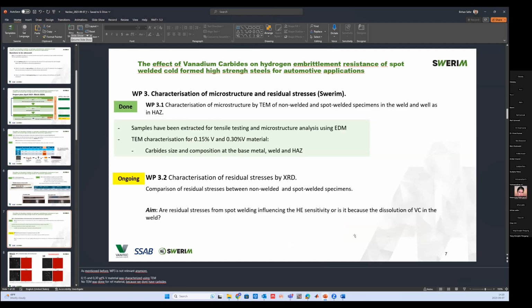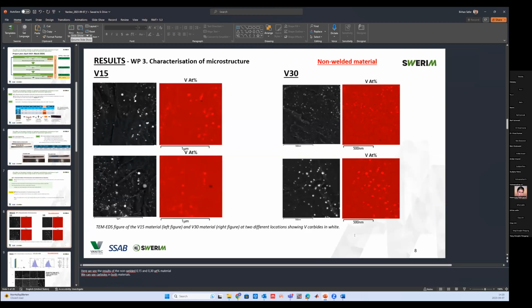So when it comes to the step of characterization of the microstructure and residual stress, in this work package we basically employ TEM, carbon replica method, to study the carbides. We have analyzed the carbides in non-welded conditions, so after processing or in the as-received state of the material, but also in the welded zone and in the heat affected zone after spot welding. The second part of this work package is related to characterization of the residual stress with XRD, where we did some preliminary measurements that I will show today. So let's start with the microstructural characterization.